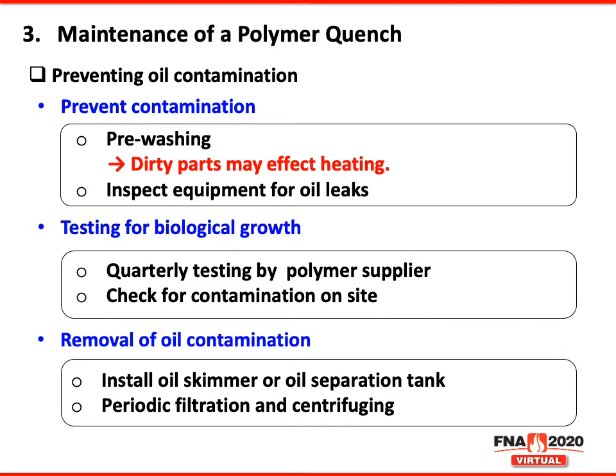So, maintenance of a polymer quench. Pre-washing is important. You want to make sure that whatever your parts are coming in, if you're a commercial heat treater, it's washed off before you apply your polymer quench. If you're a captive, you want to make sure that whatever process was used before the polymer quench is washed off. You want to check quarterly for your biological growth. You can check contamination on site. It's very easy to do.